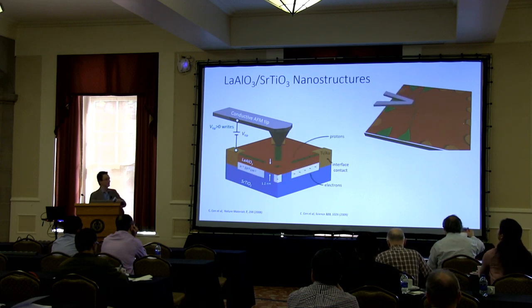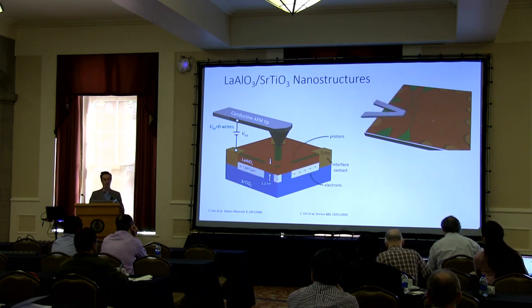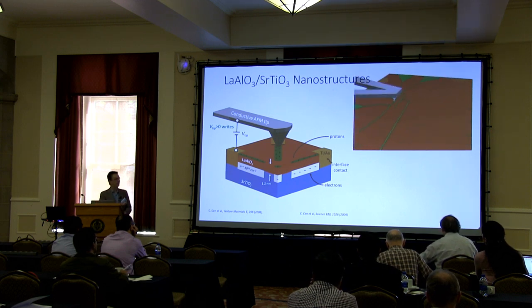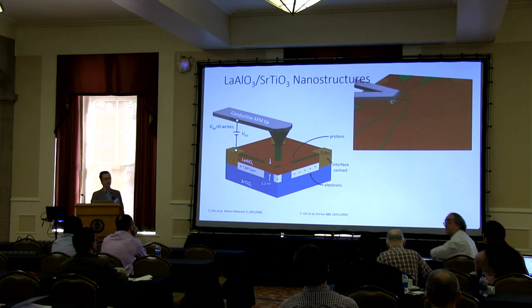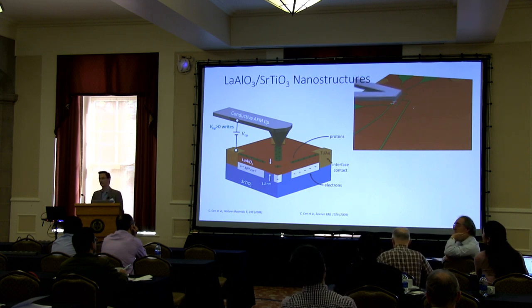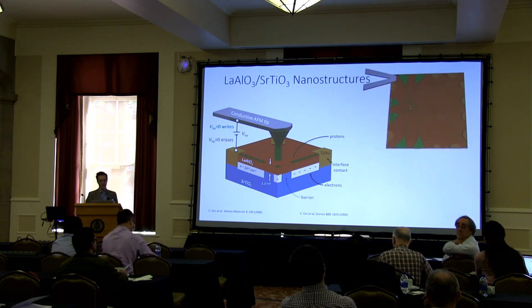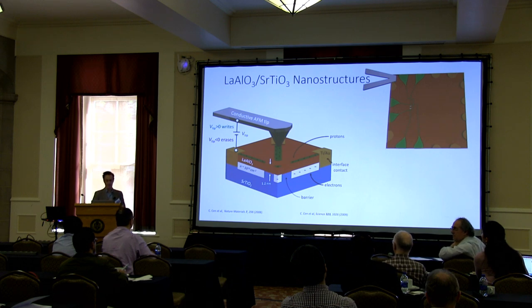And this happens through a protonation process, which I won't go into because of time. But basically, we put protons from water on the surface, and they attract electrons to the interface. And they locally switch the interface from the insulating state to the conductive state. And we can also reverse this process. So we can write, and we can do this with very high resolution.